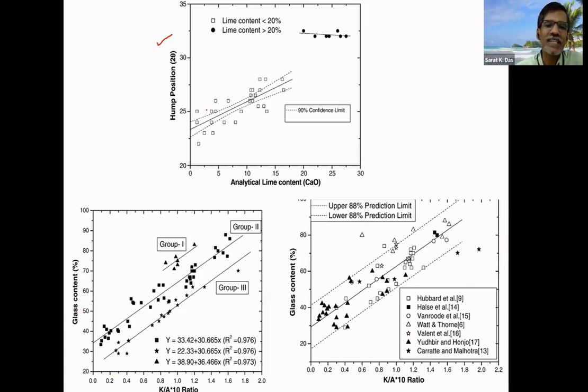Then that is qualitative. As I said, depending upon the calcium oxide, the quality of the glass changes from aluminum silicate to calcium aluminate type. But to quantify it, we found a ratio, potassium content by aluminum content, normalized with its molecular weight. Then there is a linear relationship with the glass content. That means this is qualitative and this is quantitative. And more glass content means better fly ash.